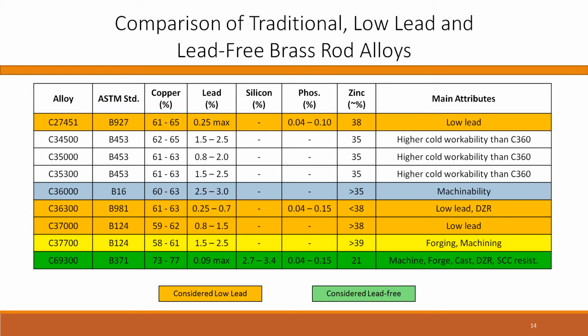For rod alloys in particular, what's really shown up as ones that are well utilized are shown in this table, and you can see alloy 360 is in blue. It's got about 61.5% copper, about 2.75% lead. The balance is zinc, and it's a machinable alloy, and you can do some thread rolling with it.